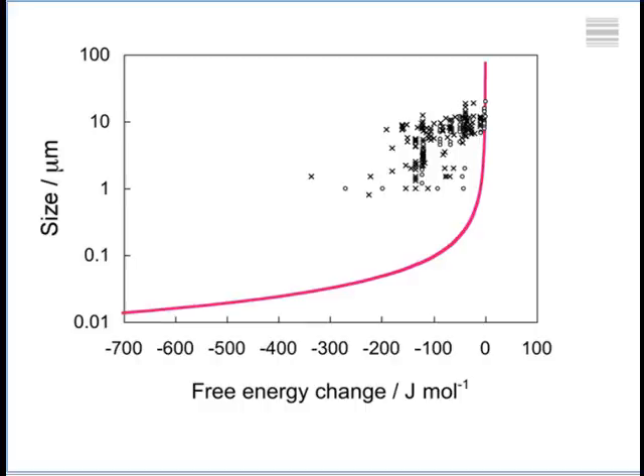These are data I've collected from the literature on thermomechanically processed steels. And you can see that they basically stop at about 1 micrometer. So the steel industry is not doing a good job, because we could actually go much finer in grain size. And according to this, I could even get to 0.01 of a micrometer. So there must be some problem as to why we are stuck at a grain size of about 1 micrometer. And that must be quite a serious problem, because there's a huge amount of money invested in thermomechanical processing.